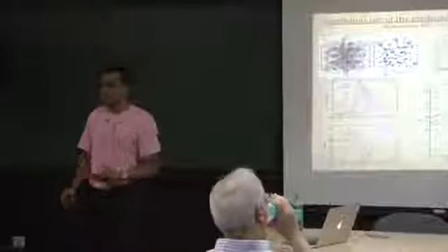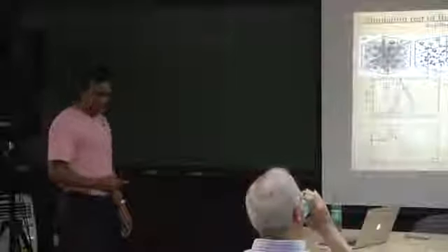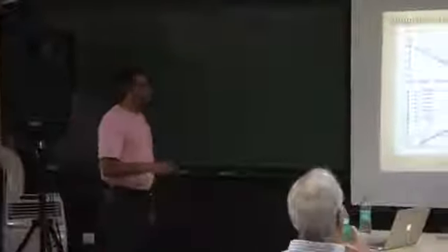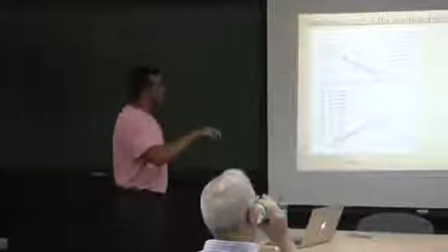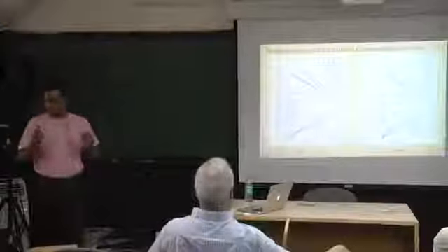And then we thought let's look at this from a dynamic perspective for a bigger system size. We did simulations of this Kob-Andersen model with, let's say, 1000, 2000 particles, for all pinning configurations up to 20%, looked at the corresponding time scale, and then fitted it with Vogel-Fulcher-Tammann, which as we discussed is not the ideal thing, but gives you an upper estimate of a divergence.